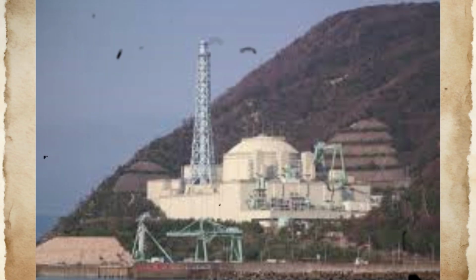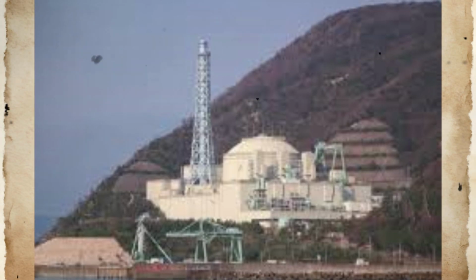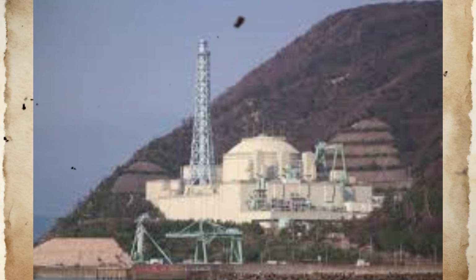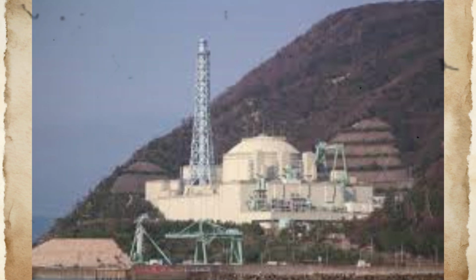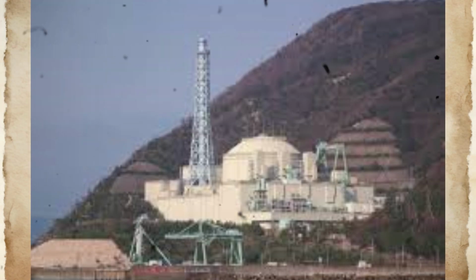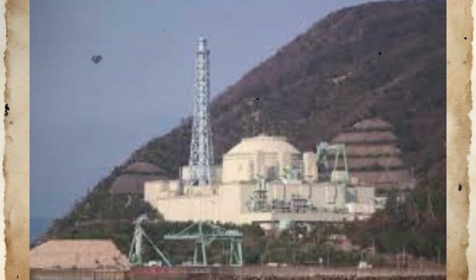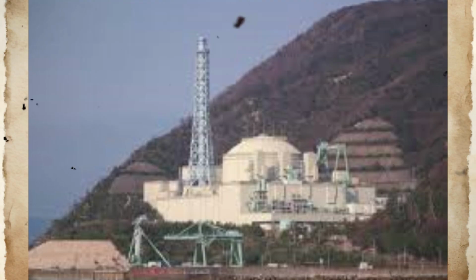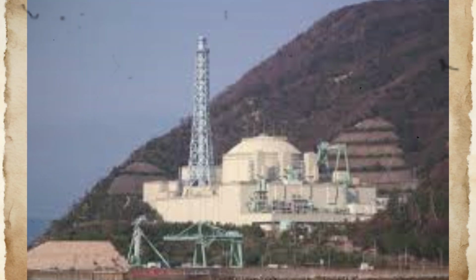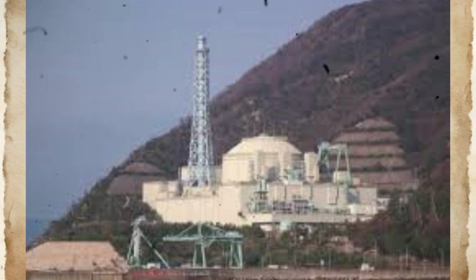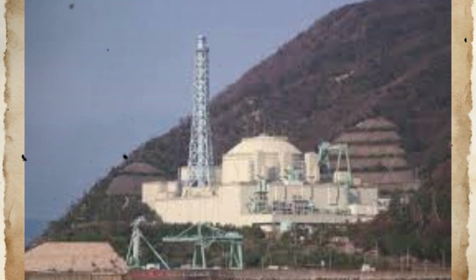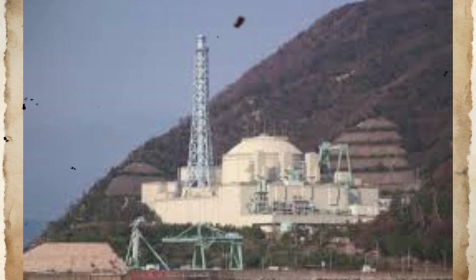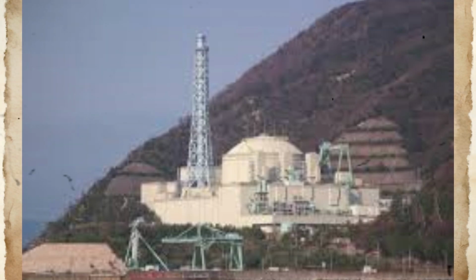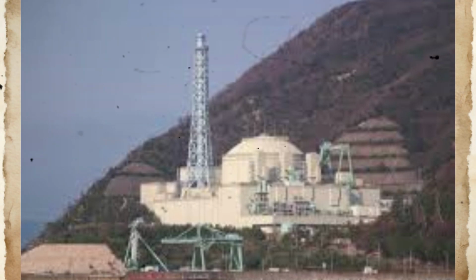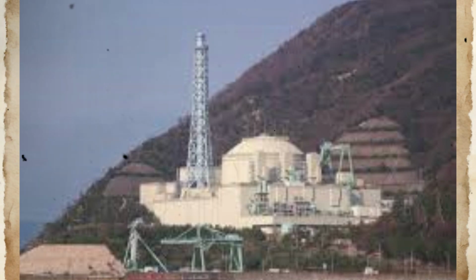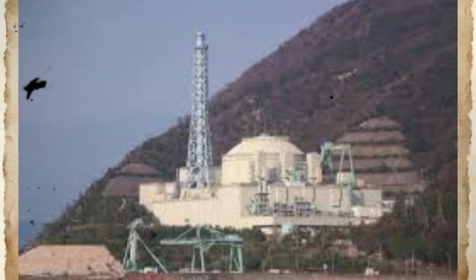The chemical physics of sodium-air reactions proceeded according to well-established thermochemical principles. Primary oxidation reactions produced sodium oxide, Na2O, and sodium hydroxide, NaOH, as the dominant products, with reaction rates enhanced by the high surface area created when liquid sodium was dispersed as droplets and films throughout the piping room. Secondary reactions between sodium compounds and atmospheric carbon dioxide produce sodium carbonate, Na2CO3, and other derivative compounds.